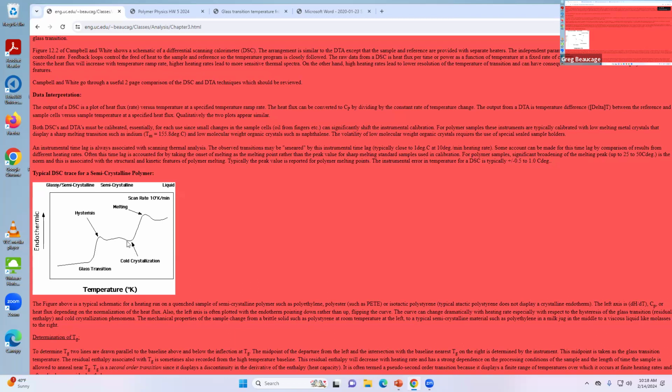So you'll see a dip in this, where it's releasing energy to crystallize, whereas it's absorbing energy to melt. That's called cold crystallization. So you have your water bottle, heat it up, and you see a glass transition, a step change in the heat capacity. Then at some point you reach the maximum rate of crystallization, a dip where it's releasing energy to crystallize. Then you get to the melting point and it zooms up, and you get an enthalpy of melting. After that you just have a liquid with a constant heat capacity. So that's the picture of a polymer in the DSC.